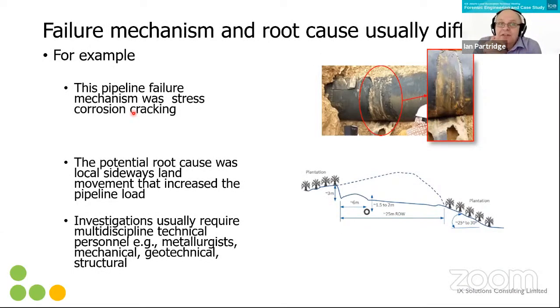So failure mechanisms and root cause are usually different. Here we've got a pipe that failed, a seam weld where there's a crack, and this crack was generated by stress corrosion cracking at the seam weld. But the root cause wasn't stress corrosion cracking. Stress corrosion cracking was the failure mechanism. The root cause was that the pipe bent due to land movement and caused a very large over yield stress. So locally it bent, a bit like your ruler. You bend a ruler and the stresses were over yield. The environment got to the steel and caused stress corrosion cracking. So the root cause was the land movement.